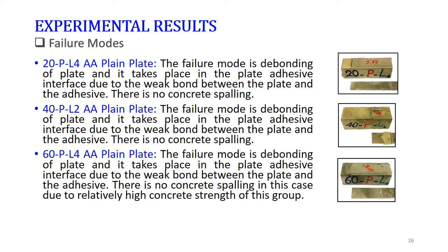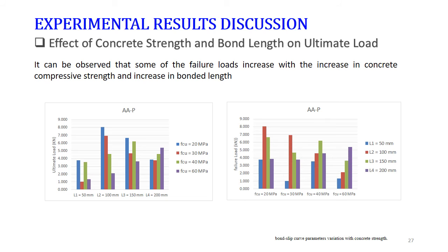And actually we have other experiments we did in which the surface of the aluminum has been treated, and that shows a big difference in terms of the shear resistance after treating. Okay, here I show you some of the tests summarized, for example, the concrete strengths and bond strengths and their effect on the ultimate load. And you can see that sometimes you see a trend, and sometimes the trend is not there, because debonding is a premature failure, so it doesn't really tell you the whole story sometimes, but some of it shows you some pattern.